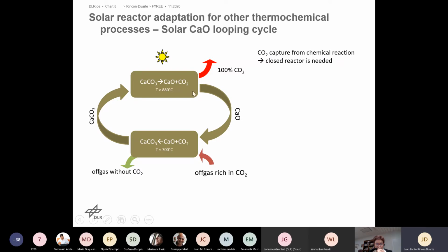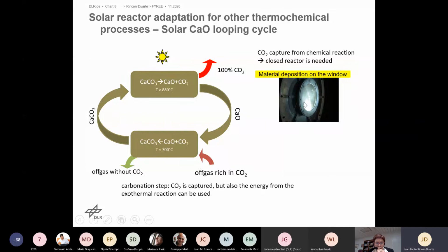One advantage of this cycle is that with the solid product, the calcium oxide, we can use this material to absorb CO2 from, for example, an industrial flue gas, and this is also an exothermal reaction, so we can use the energy from this reaction. But as I mentioned before, one challenge for the rotary kiln to be used in this cycle is to operate in closed mode. For that reason, we put a window on the reactor front where the solar radiation enters.